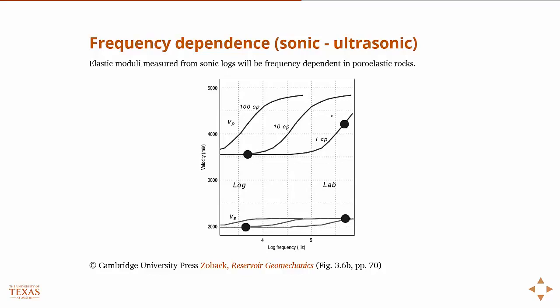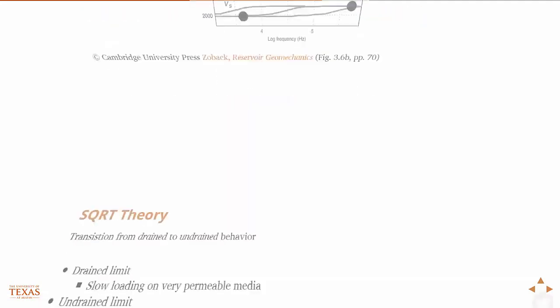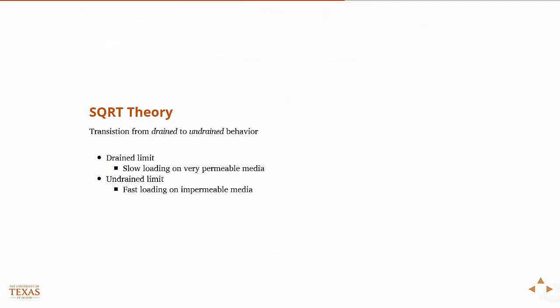So when you propagate a wave, you're elastically deforming it a tiny amount. You'd never be able to see it, but the frequency of that wave affects how fast you're loading it. And then what you see is this transition from the drained to the undrained behavior. That's why these two limiting plateaus are in the frequency response.